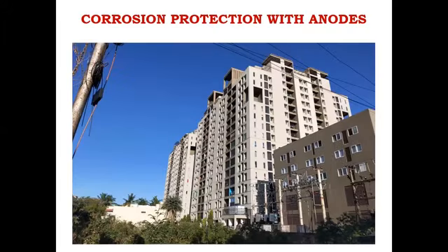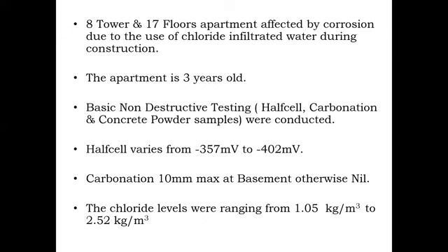As I said, this particular structure is hardly 3 years old, but it has a lot of corrosion in the columns, mainly underneath the sunken portions, and it has about 8 towers of 17 floors each. When you go for non-destructive testing, the half-cell values vary from around minus 357 to 402, but carbonation is only 10 millimeters, and that too only in the basement 2 level, where cars have been parked and a number of vehicles have been used.